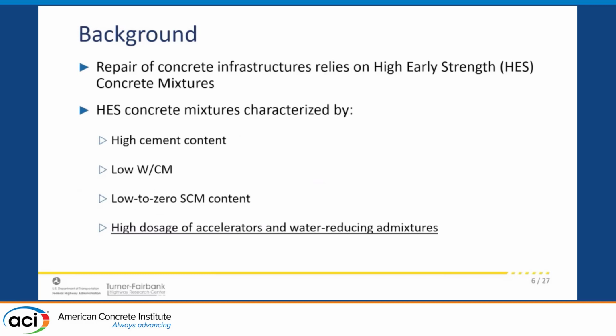So why are we performing this work? My general topic for my PhD thesis is repair materials, specifically for full depth repairs. What we typically observe being used in the field are these high early strength concrete mixtures. The way we design this concrete mixture is by having very high cement contents, very low water cement ratio, basically no SCMs, and very high dosages of accelerators and water reducing admixtures. All of this is combined to try to generate as much PSI as possible within just a few hours. These mixtures can reach 4,000 PSI between 6 to 8 hours from initial mix.